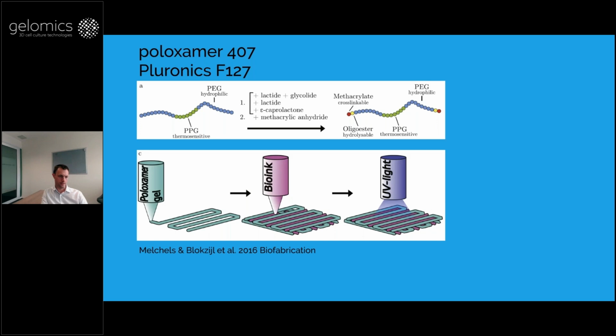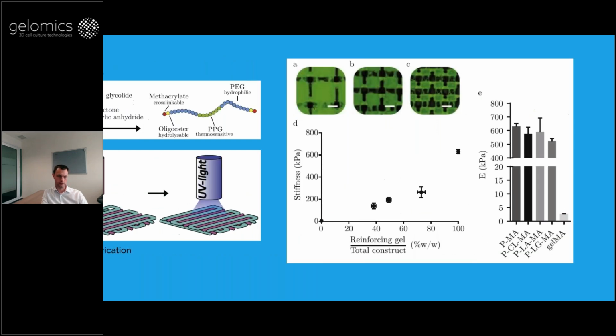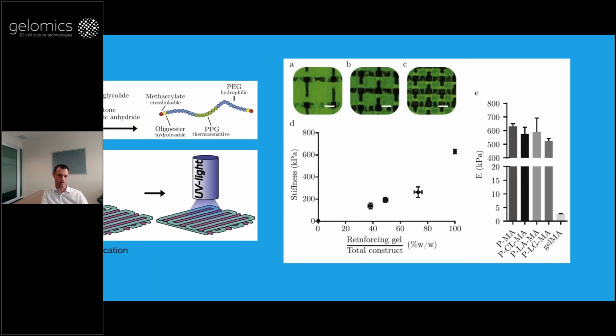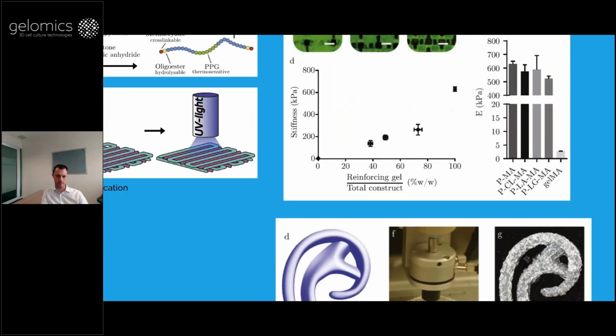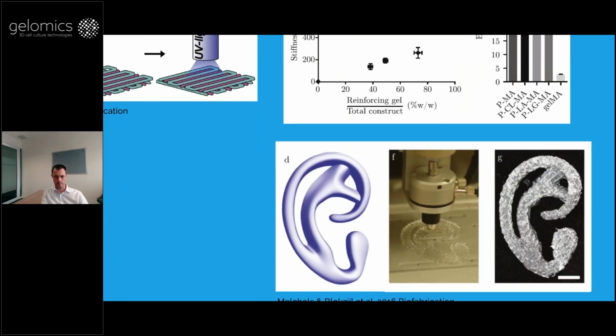And then we could print this together with the bioink with the cells, and the bioink was just plain GelMA, liquid at 37 degrees, to fill the gaps. Here we use FITC GelMA, so you can see the GelMA in green with the reinforcing ink. And by using more reinforcing ink, you can get a higher stiffness. You can see here that it really keeps the shape. This is about a 50-50 construct, and you can print shapes and build up to higher structures despite the gel not being self-supportive.